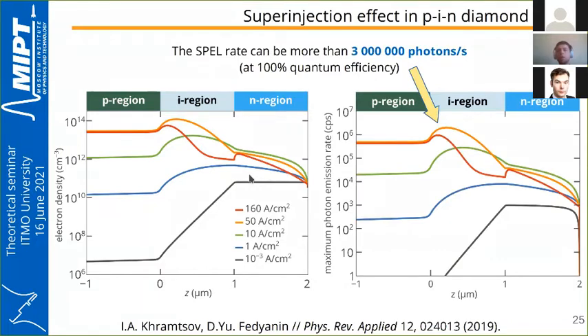Now, the single-photon electroluminescence rate in diamond diodes depends mainly on the electron density. If we plot the dependence of the single-photon electroluminescence rate on the position of the color center within the PIN diode, we see that for color centers located near the potential well, the center will emit more than 3 million photons per second—much better, 3 orders of magnitude higher than the doping limit.